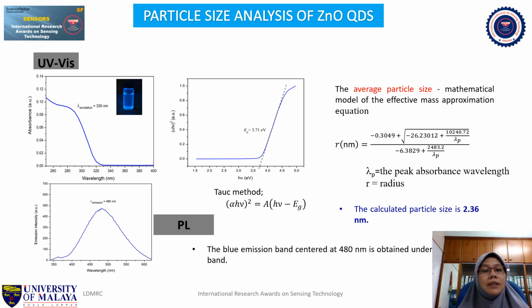From the absorption spectrum, we can also determine the energy band gap of the quantum dot. In this case, we found that the energy band gap is around 3.7 eV by using the Tauc method, as shown in this formula here. PL is also performed for this work. We see that blue emission is obtained, centered around 480 nanometer, when the zinc oxide quantum dot is excited at 330 nanometer wavelength.